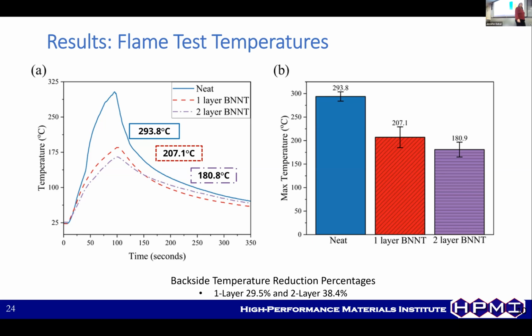The promising thing we're looking for is we want that backside temperature to be as low as possible. Because the backside is where we have our structural materials, we don't want to burn that. Imagine you're in a space vehicle and you're on the back of that. You don't want it to be over a certain level. So the exciting part is the 2-layer had almost 40% reduction in backside temperature with only 2 layers of addition. A very small amount of added material can really result in a pretty large backside temperature reduction.